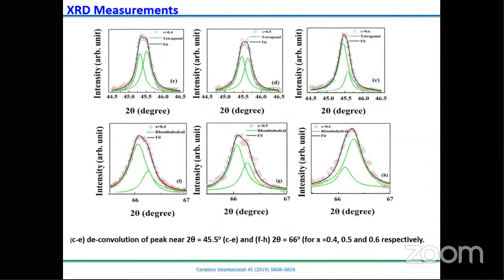To quantify that, we deconvoluted the peak by using Gaussian peaks, and here you can see those green lines are the two peaks. The discrete circles are the experimental data, and the black line is the fitted data. It is well fitted with our experimental data. Therefore, we can conclude that each peak contains two peaks. Those are the two peaks we have shown here.